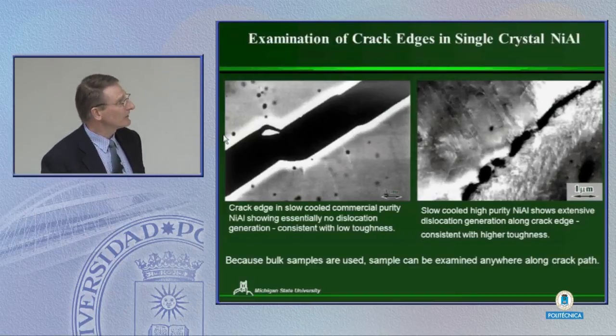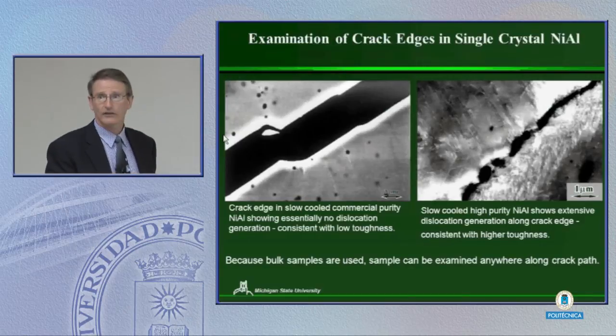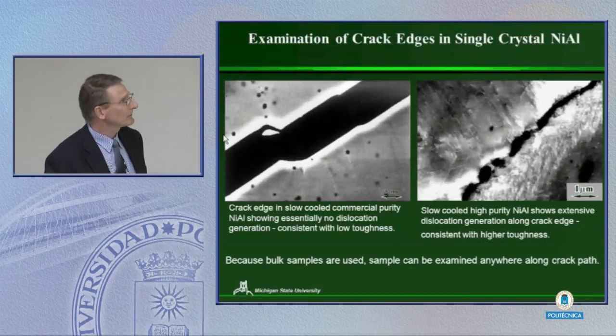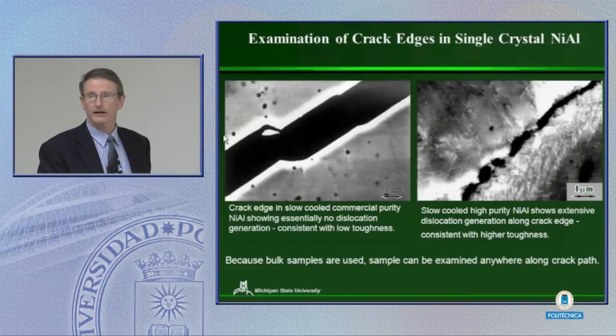The other thing that's interesting to note is how the dislocations are significantly different on either side of the crack. And we haven't characterized these fully, but certainly these dislocations are more or less end-on, so they look like points. Where these dislocations here are lying in the plane of the sample, and certainly aren't lined up in these same sorts of slip bands along here.